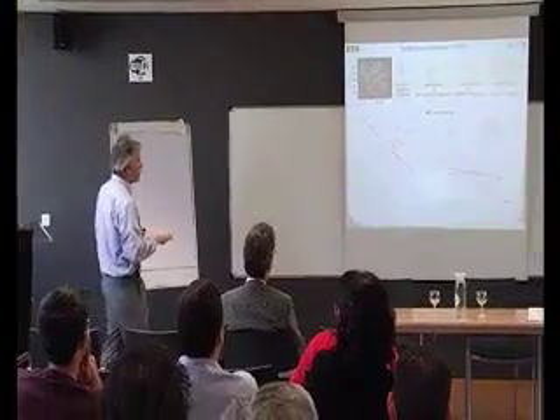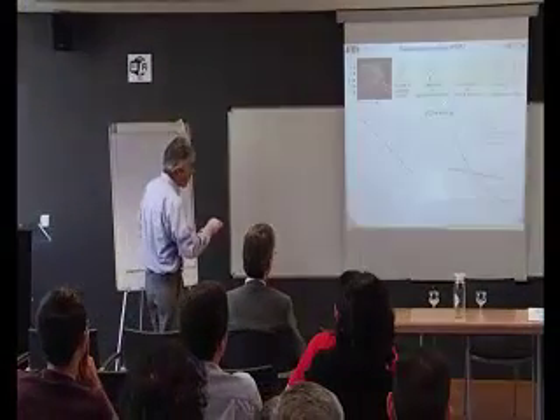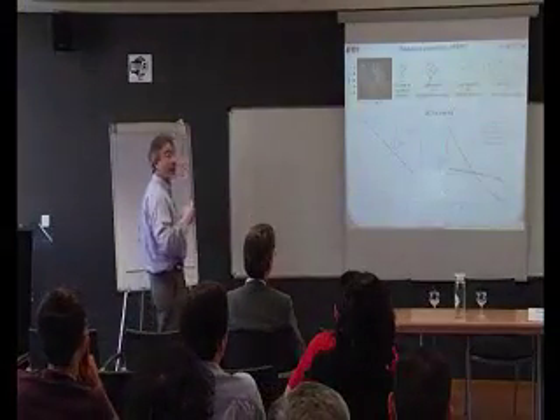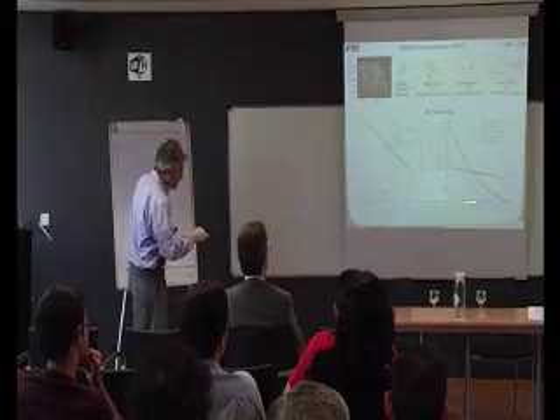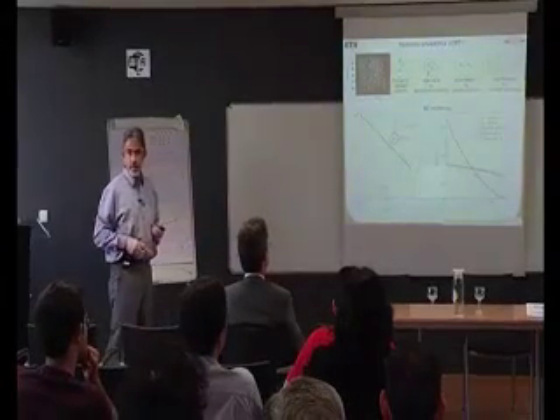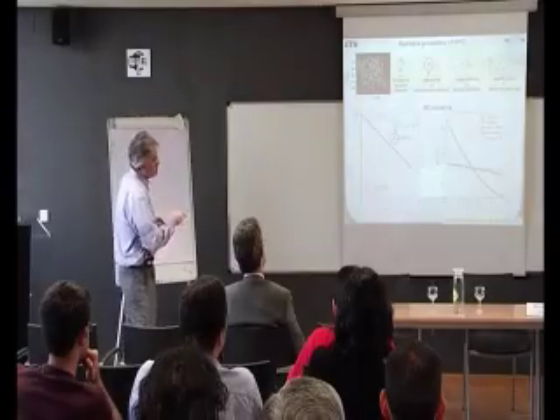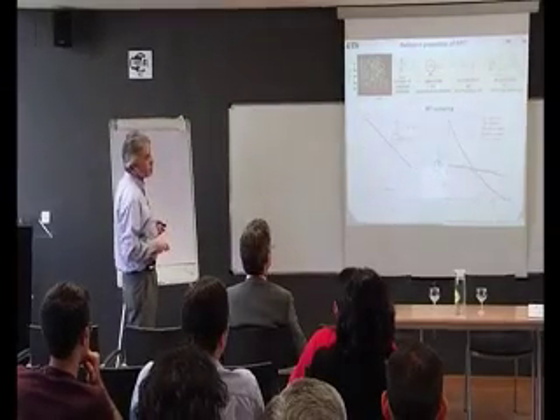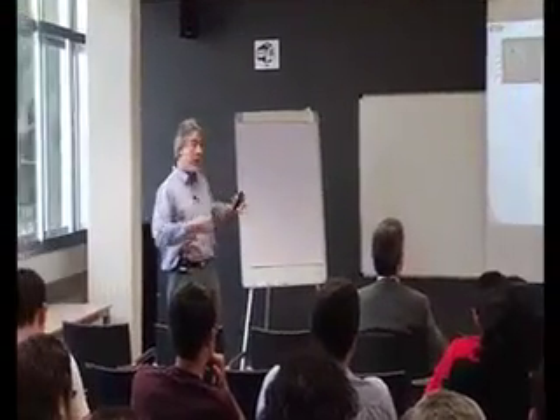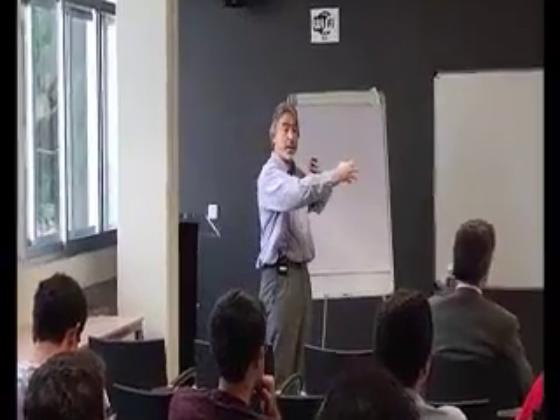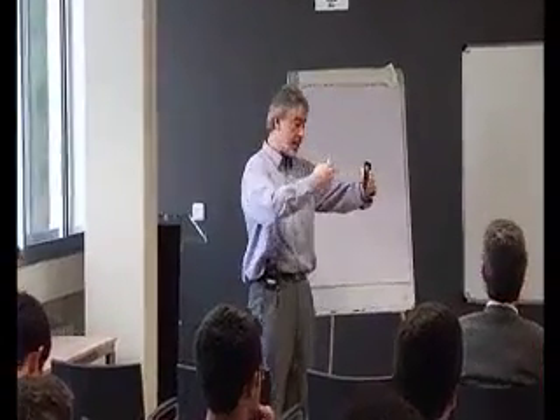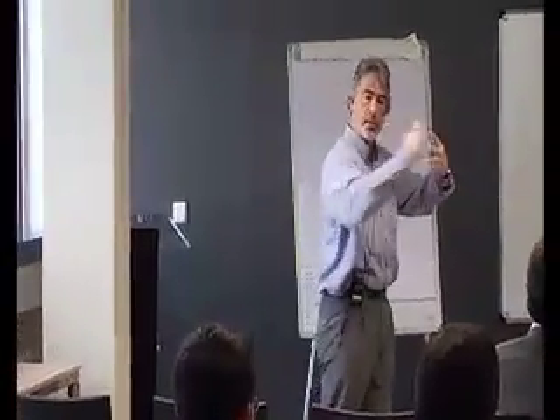We can do the same by plotting the probability of reflection in a given direction as a function of the cosine of this direction. And this is nothing else than the scattering phase function. So we can proceed and solve this equation numerically at the pore level and understand how radiation travels through the material.